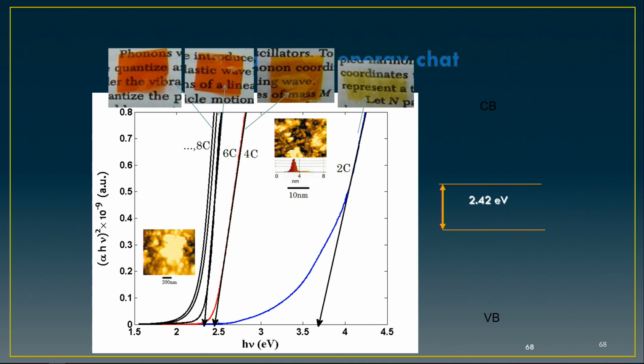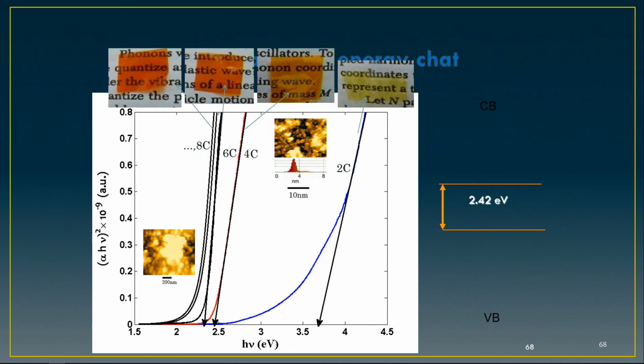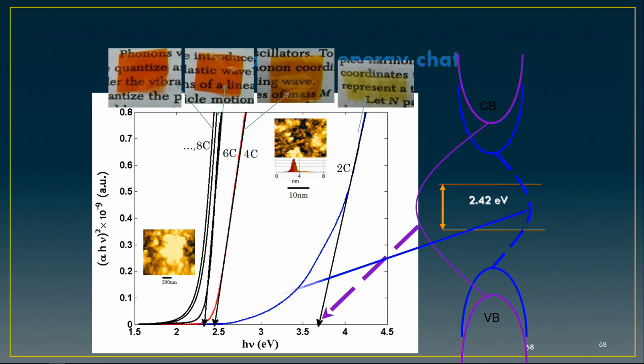2 cycles, 4 cycles, 6 cycles, and 8 cycles of SILAR. By increasing the cycles of SILAR, the band gap is red shifted. In the case of 2 cycles, we have very small nanoparticles inside the polymeric materials. And by the growth mechanism, the band gap of the semiconductor nanostructures shifts to the red region. This is the band gap of the nanoparticles for 2 cycles, and for 4 cycles, and also we have a redshift here.